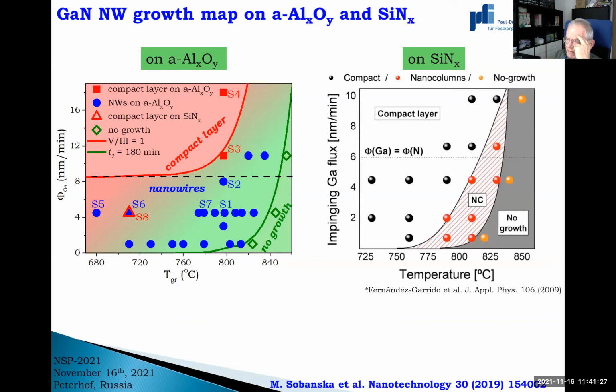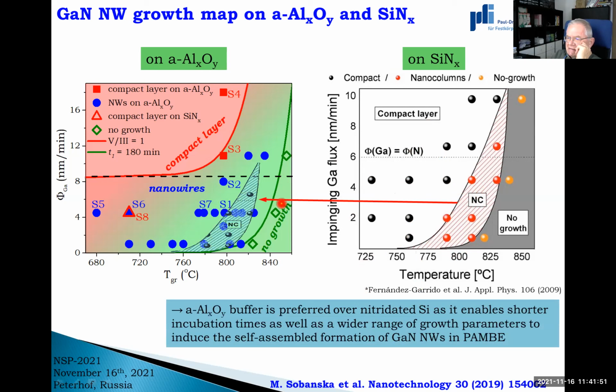Now let's have a look at the same thing on silicon nitride. This is a map prepared and published by Sergio Fernandez Garrido. Again, you have the compact layer regime, no growth, and nanocolumns in his case. In order to make a comparison, we just adjust the axes, and you see that on silicon nitride, this is the range of parameters available for nanowires, while on aluminum oxide, this range is much wider. So this tells us that the aluminum oxide buffer is preferred over silicon nitride, since it enables shorter incubation times and a much wider range of parameters under which nanowires can be formed.